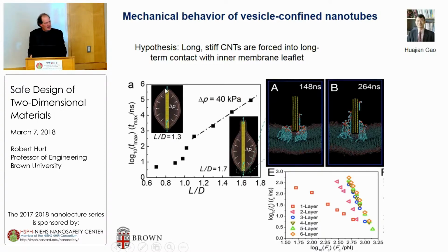And Huajian's work took these simulated nanotubes and put them inside lysosomes and tried to figure out what was causing the damage. And the simplest idea was if the tube gets long enough, it punctures the lysosome and out come the contents. But in his simulations, he could never make that happen. Instead, the lysosomes, and these are just vesicles really, take on a kind of a pear shape and then a cherry shape. They're happy to conform around the tube rather than be punctured by it.